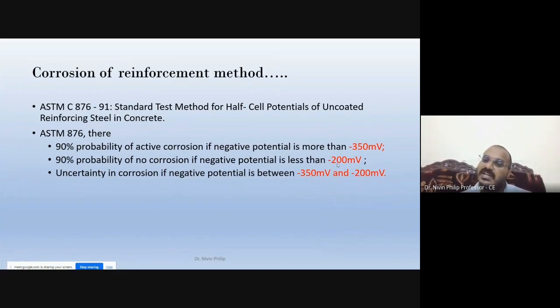If it is less than minus 200, then there is a 90 percent probability of no corrosion. So in between, we cannot identify how much corrosion has happened, or whether we can retain that reinforcement. It's a gap in between: it should be either 90% good or 90% bad. So there is an uncertainty in this value.